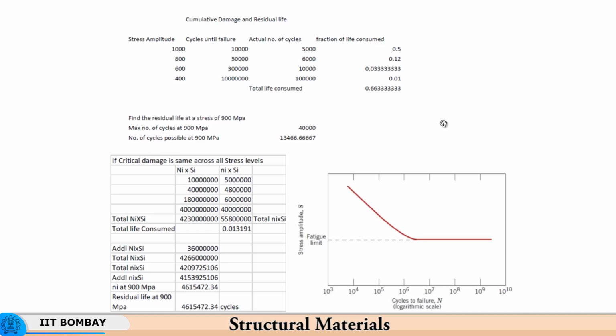So, that is why we accept it, but normally there are many interacting factors which would affect the cumulative damage, the life, etc. But then to keep the formula simple, to keep the analysis simple, we have a linear addition of these damage accumulated under different conditions, and determine the residual life. Anyway, it is an estimate. We are always going to be lower than that, because we are not going to exhaust all these 13,466 cycles, but it gives me a ballpark figure as to what the fatigue life is going to be.